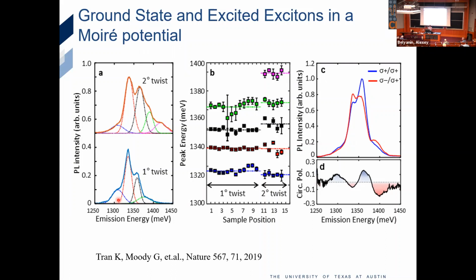Yes, please. Good question. This is about 20 Kelvin. So we're not going to the extreme of 100 millikelvin yet. But also, this transition is stable at room temperature. They will survive at room temperature, except the line width will get broader because of interaction with phonons. Then again, we lose track of this discrete resonance.